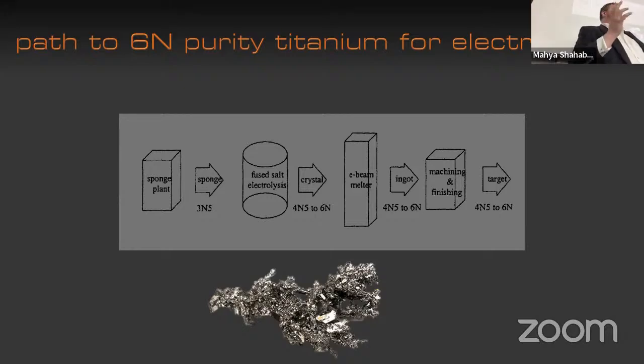And remember, this is early 90s, so ancient times. But aluminum line widths were getting narrow enough that they couldn't put aluminum directly on silicon, because aluminum and silicon actually don't make a great interface. And so you start to get shorting across. The difference was you put titanium in between there, and TiAl3 and TiSi2 have nice interfaces. Eventually titanium was replaced with tantalum, all of this evolution as you get to finer and finer line widths. But that was the motivation for having a sputtering target with very high purity, so that in microelectronics you aren't getting other impurities in there messing up your communication. So that was the motivation.